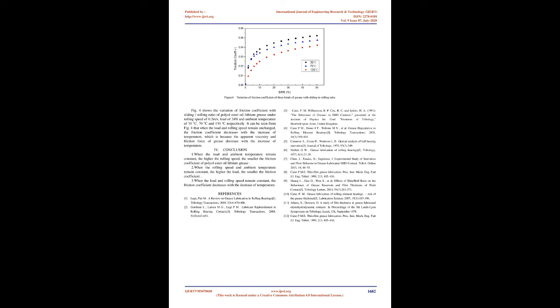Figure 3. Variation of friction coefficient of 3 kinds of grease with sliding to rolling ratio. Figure 3 shows the variation of friction coefficient of polyol ester lithium grease with sliding to rolling ratio when temperature remains constant. The ambient temperature is 30, the rolling speed is 0.2 m/s, and the load is 24 N, 38 N, and 70 N respectively. It can be found from Fig 3 that when the rolling speed and ambient temperature remain constant, the greater the load, the smaller the friction coefficient. This is because the greater the load, the greater the friction resistance of the contact surface.